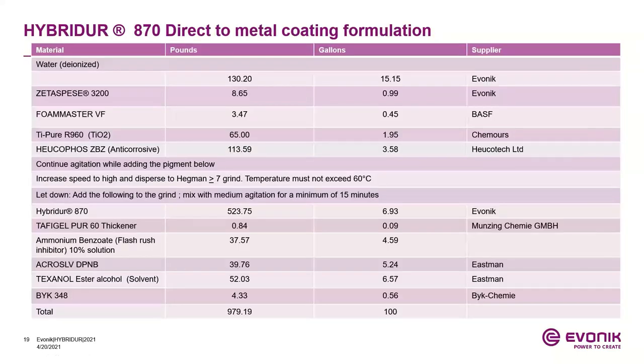Hybrids are also typically used in direct metal coating formulations. In this case, we use a zinc phosphate, Heucophos ZBZ, anti-corrosive pigment with titanium dioxide. This is also a resin-free pigment grind. Zetaspese 3200 is dispersed in water to get a Hegman grind of at least 7, and the temperature must run around 60 degrees. Again, the formulating is fairly simple, as with the previous one.